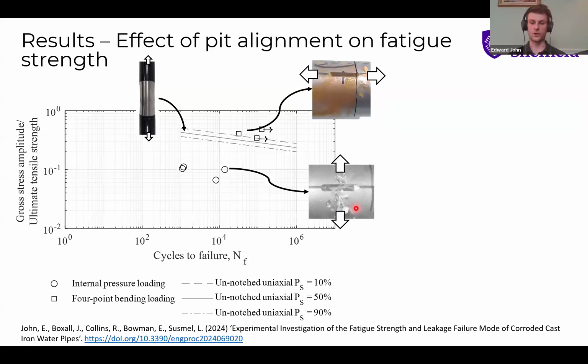The next set of tests were looking at the shape of the effect of pit alignment. So those previous pits were symmetrical. Then we looked at these axially aligned pits. So again, we've got our reference curve here, which is just the uniaxial fatigue curve, so the tension compression with no pits at all.